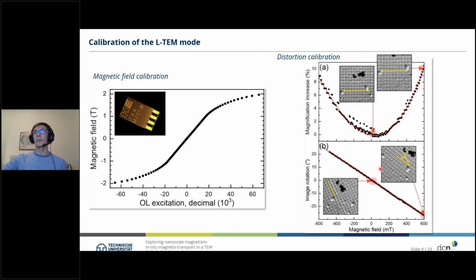Another thing we need to take care of is a variation in the magnification of our image. You can see that by looking at the cross-grating, which we used here for calibration, that the distance is different for 0 magnetic field as compared to 600 milli-Tesla. The spacing gets larger and we have an increase of magnification in the order of up to 10%. But since we calibrated that as a function of the magnetic field, it can also be used for rescaling the images in post-processing.